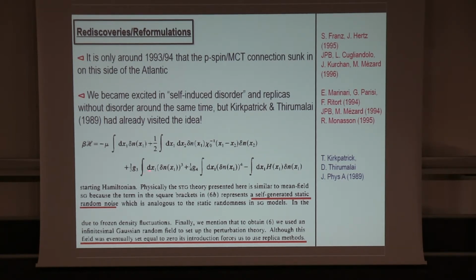And everything is there. So this is a density functional Hamiltonian for the glass. There's here a random field term that's added. And if you read the paper, they speak about self-generated static random noise, which is the same as self-induced disorder. And they also say something that we realized later, that adding some randomness and then putting the randomness to 0, which seems weird, is a way to use replicas and get something non-trivial doing that. So, 89.